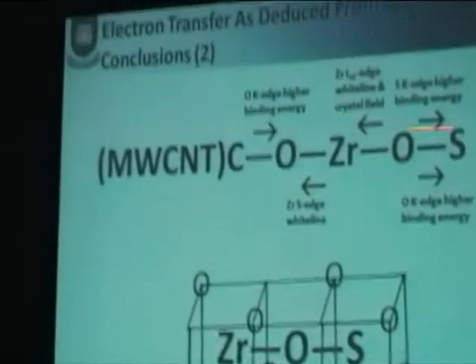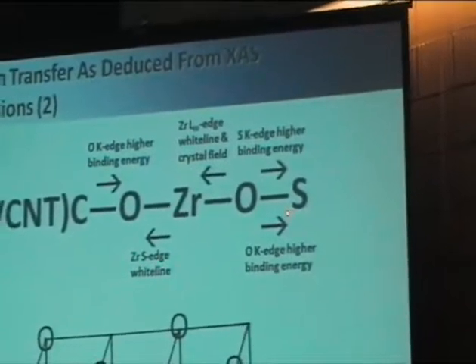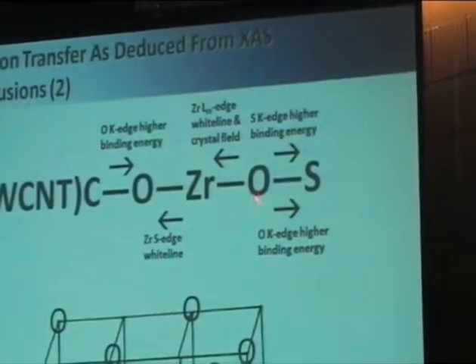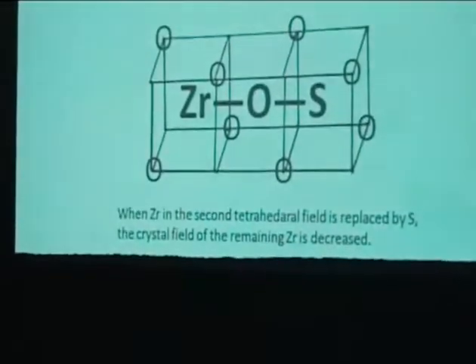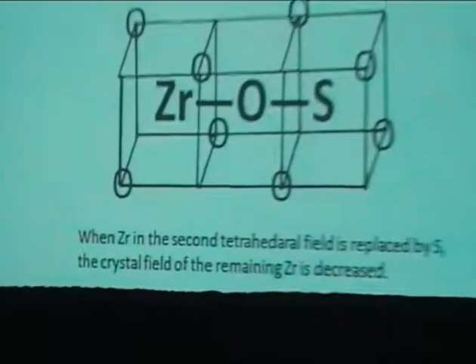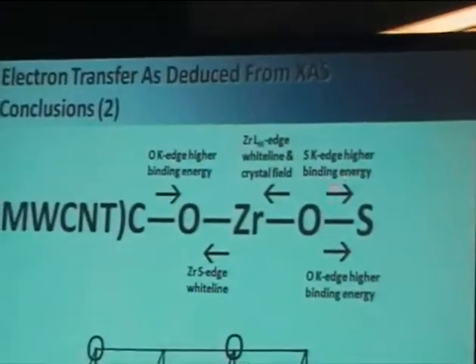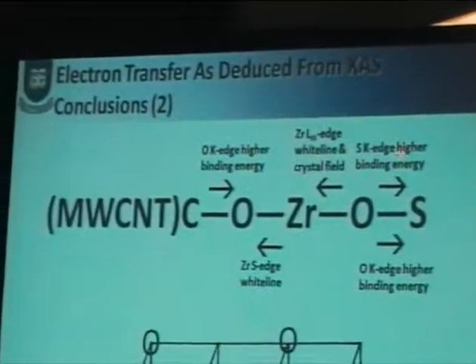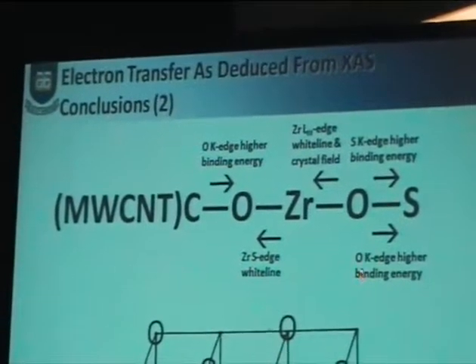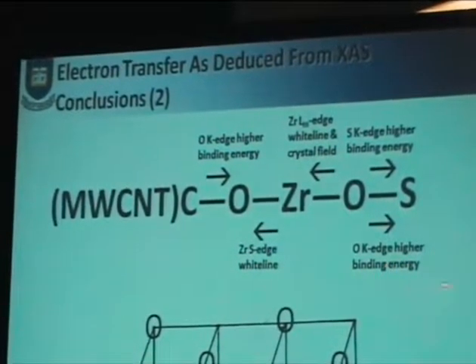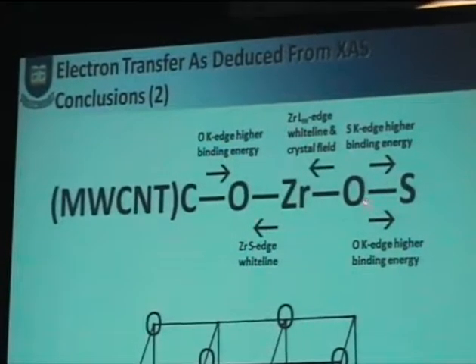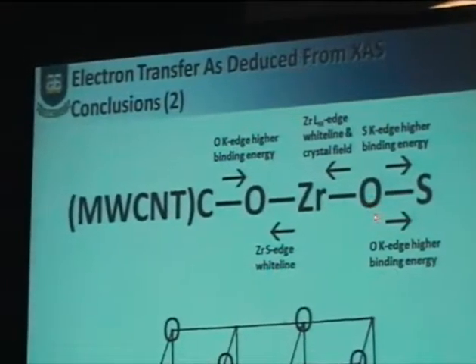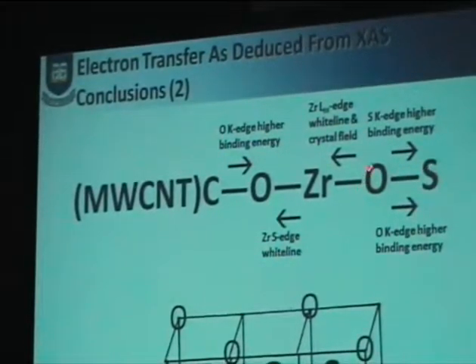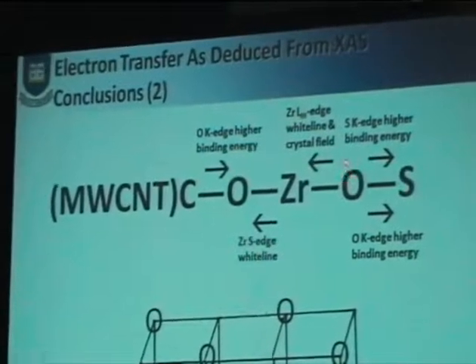So this is all of this electron shifting that we've looked at. It's not a simple matter, as I took from that review article, showing that there's charge transfer from sulfur to zirconia. In fact, looking at the K-edge, the binding energy of sulfur and also the oxygen K-edge shifting to higher binding energy, those all say that there's electron density from oxygen to sulfur, but also electron density to zirconia.